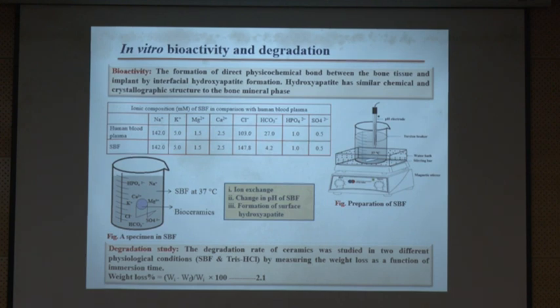So what happens? You are immersing your pellet into the SBF, and there is an exchange of ions. As a result, there will be a change of pH and a change of degradation. All these are the tests to confirm whether the material is active or not. So that's what you are doing here, checking whether the material is active or not in terms of pH, in terms of degradation.